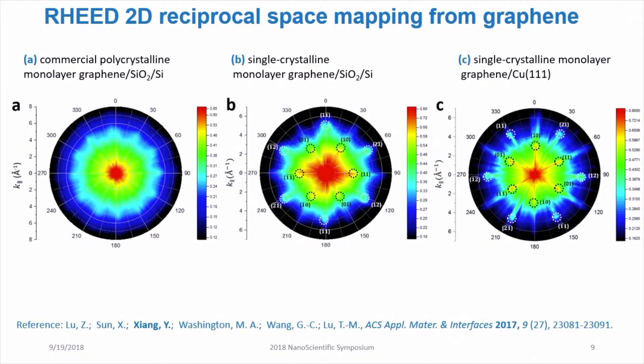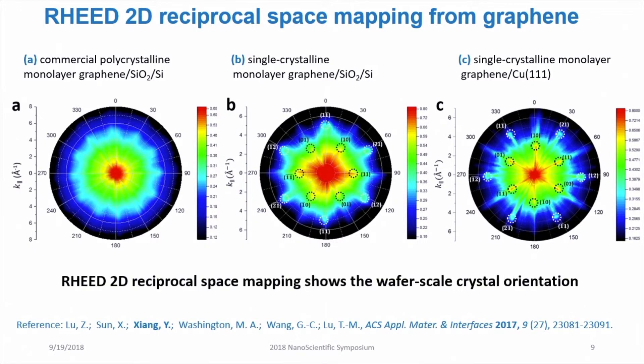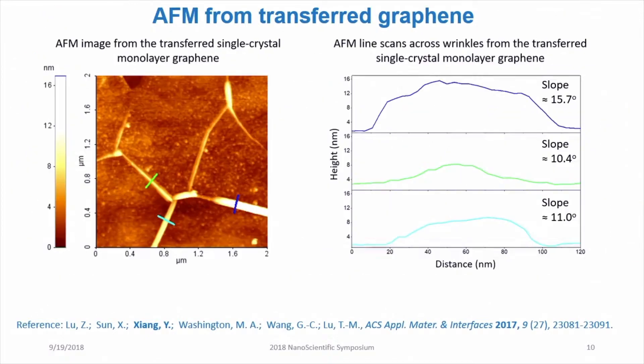A clear sixfold symmetry is the case for single crystalline graphene. From those reciprocal space mappings, we can tell that the samples corresponding to figures B and C are single crystalline, while the one corresponding to figure A is polycrystalline.